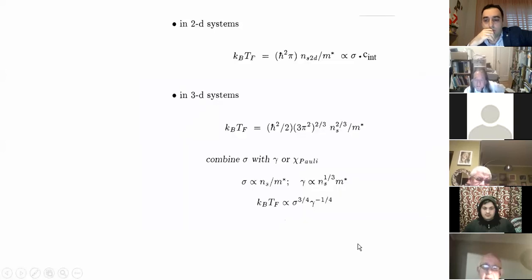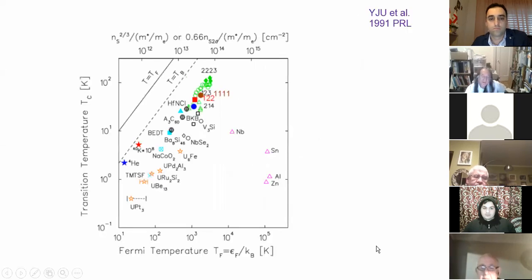And there are some three-dimensional systems. It is very well known that this Fermi temperature has a slightly different proportionality, the carrier density to the 2/3 power divided by the mass. But you can combine with some other experimental results and again obtain this typical energy scale, what we call the Fermi temperature. And it is mostly coming from, again, our damping rate of the mu-SR results. So by getting the mu-SR results, you can convert the horizontal axis to this typical energy scale of superconductors or metals. This is the plot that we obtained by doing that conversion.